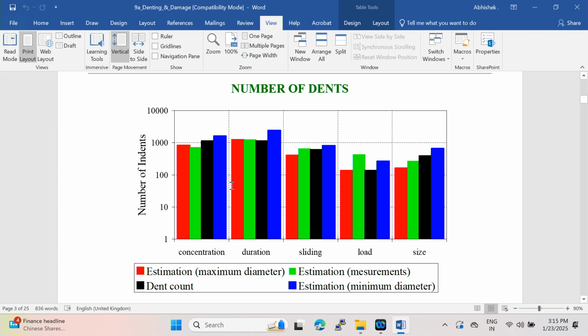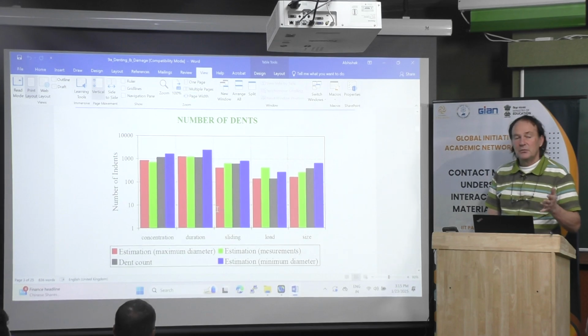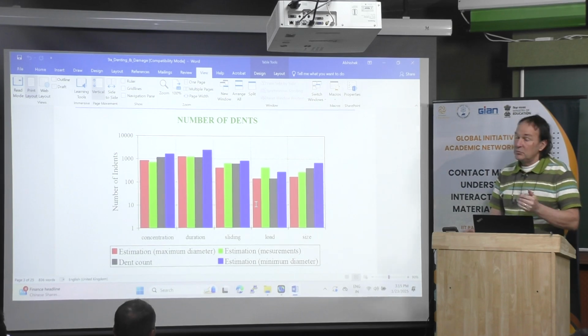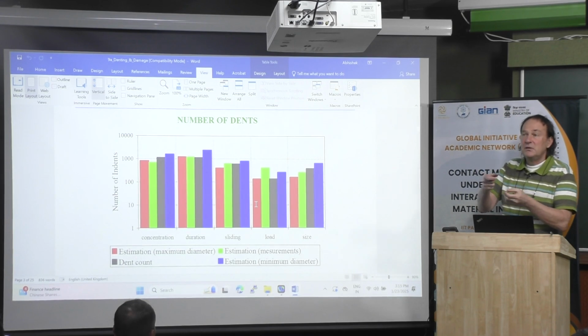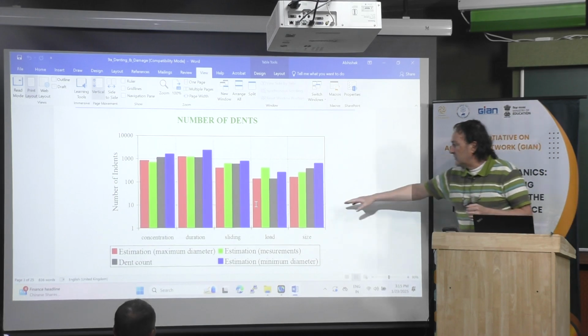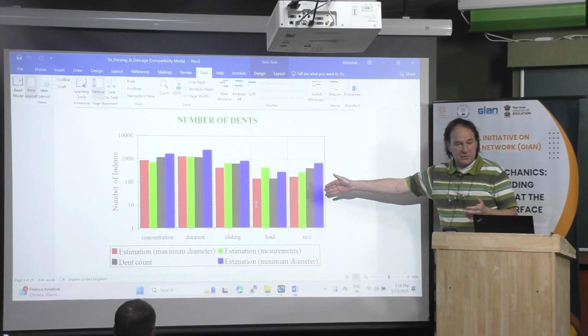Okay, and for the second test here, we change the duration of the test. For example, we double the time. We do another test with doubling the time. The third test here, we add some sliding. First it was pure rolling, after it was sliding. Here we increase the load by a factor 2 or 3 or 4. That decreases the EHL film thickness, then that reduces oil flow within the contact. And also because the film thickness is thinner, maybe you can reject some particles. And the last one is done for bigger particles and so on.